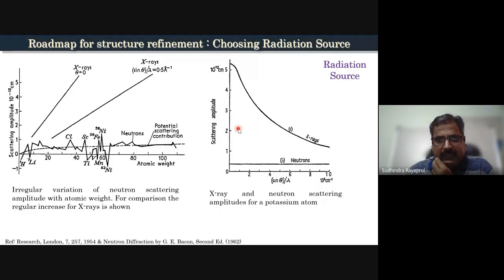Okay, if you want to compare X-rays and neutrons, X-rays have what is called atomic number dependence. What it means is that the heavier the atom, the more the X-ray scattering for that atom compared to lighter elements. In the case of neutrons, that is not the case. Neutrons don't scatter as a function of the atomic number, but as a function of the nuclear energy levels. So they have some advantages and disadvantages compared to X-rays.